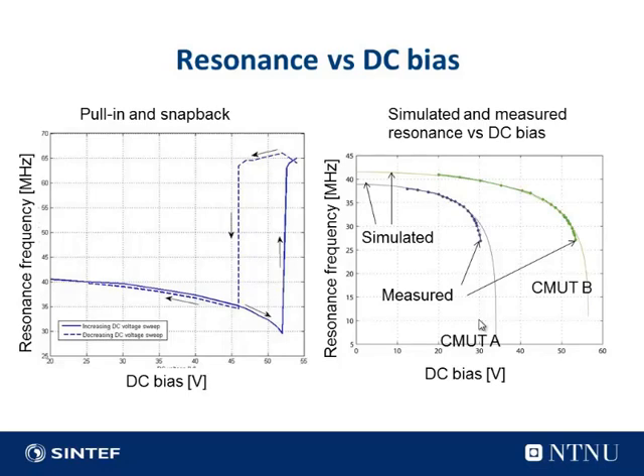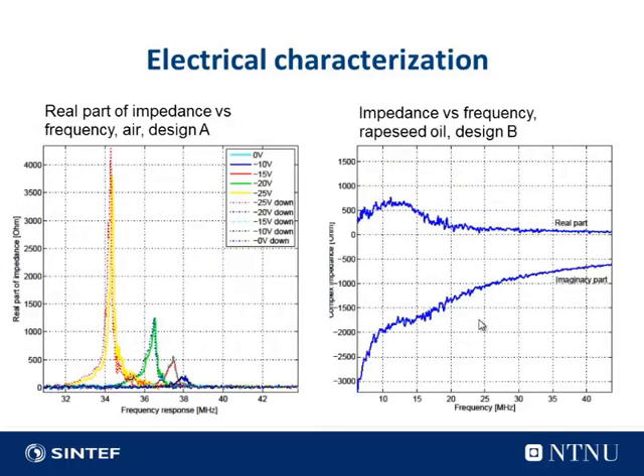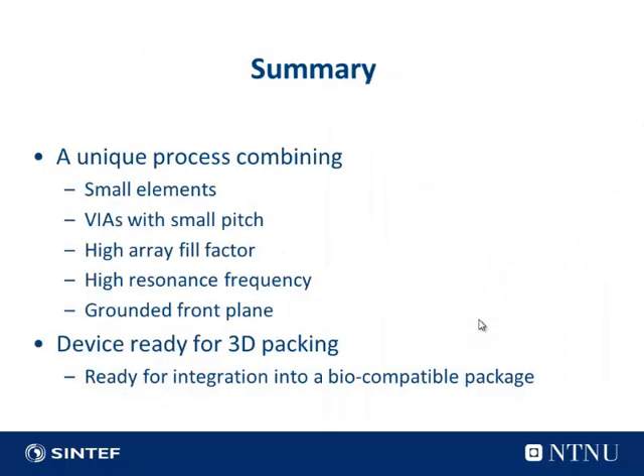For the measurements, we have done a measurement of pull-in and snapback behavior to find the pull-in voltage. We have done measurements at different DC bias. We didn't quite get the resonance frequency to correspond with the simulations. We believe it's because we haven't met the correct material parameters, but by changing them, we got a quite good match, though that was after the fabrication. Okay, since I'm just focused on this one, these are the measurements in rapeseed oil. It has pretty much the same acoustic properties as blood, so that's why we have chosen that. We reached 12 megahertz resonance, which is a bit lower than we wanted, but we still think it's possible. We know what to do to get that better.